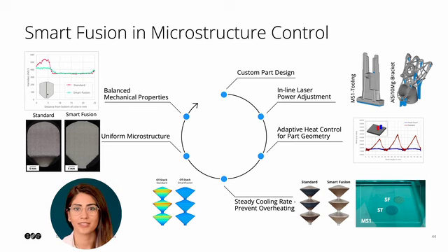For a specific application in different industries, we create custom parts with a complex shape. These shapes often have geometrical features like overhangs, hollow structures, and changes in the cross-sectional area. All these geometrical features affect the thermal behavior during the manufacturing process. With Smart Fusion, we can now adjust the laser power in real time, which helps us control the heat more precisely. This ensures a consistent cooling rate and helps to prevent overheating during the entire process.